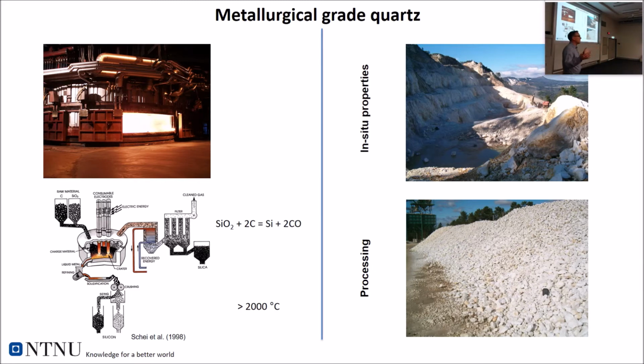The wood chips are just there for keeping porosity, because this process will create a lot of gas that needs to flow through the charge, and wood chips just open up. The quartz will, on the other hand, contribute. If it's not good quality, it will block this gas movement by decrepitating and producing fines inside the furnace that clog every porosity of the material. So that's what the thermal properties of quartz are for.